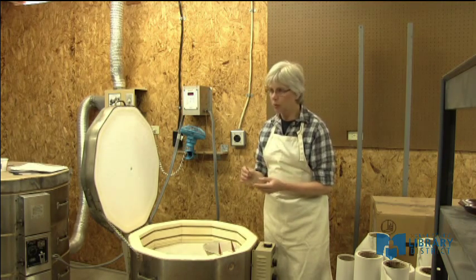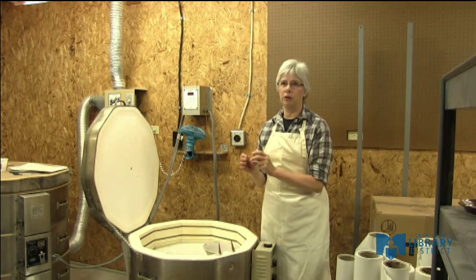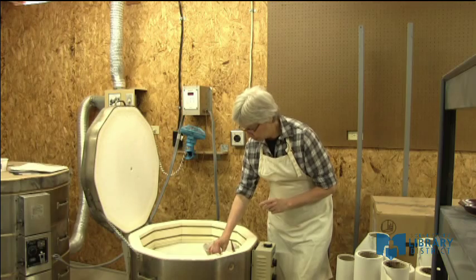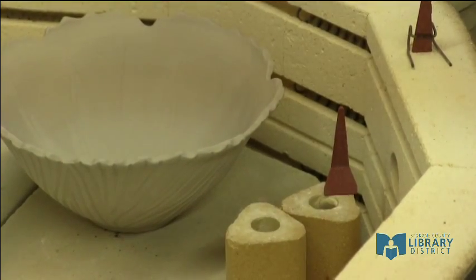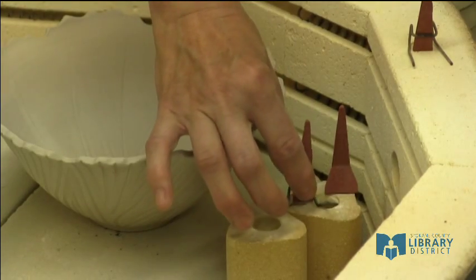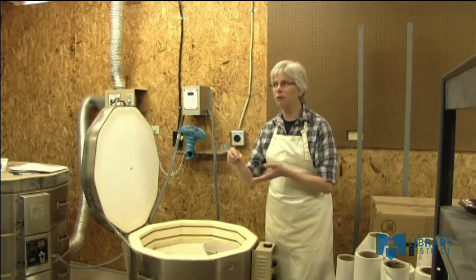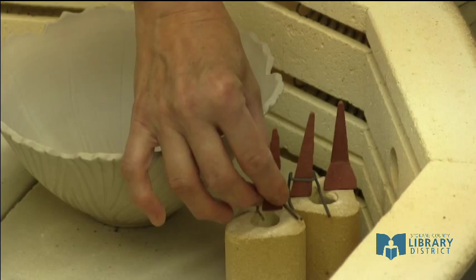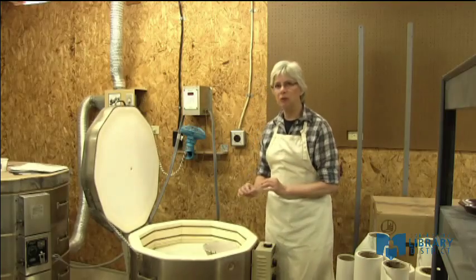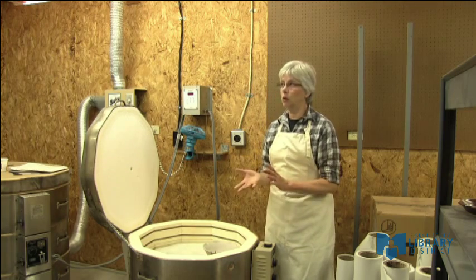The first cone I put in is the cone below where I want the final firing temperature to be. So I'll put that one in first. And then the second cone is the final firing temperature. I put that one in. And then the third cone is the one above the final firing temperature, so I know if it's been overfired. As the kiln reaches the specific temperature that that cone bends at, then I'll know where we are